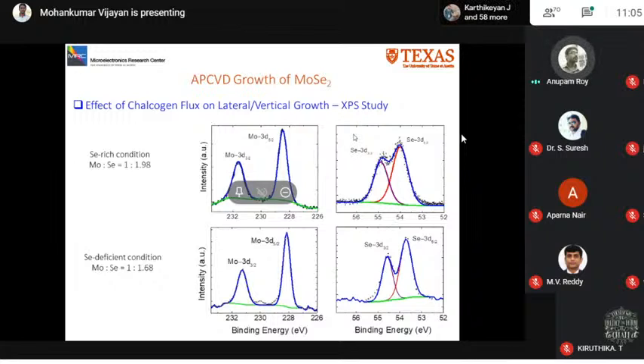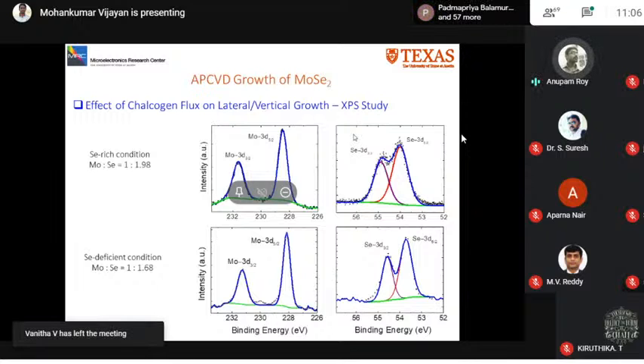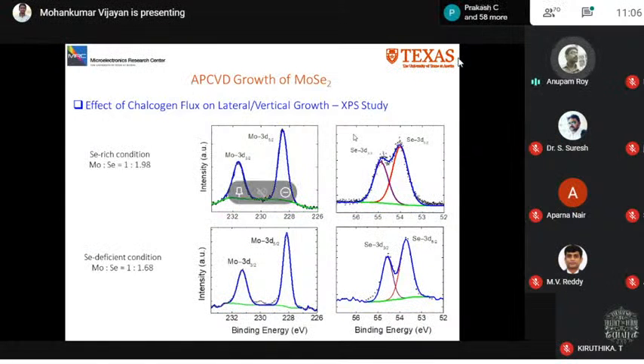For MoSe2 growth under two different environments, selenium-rich and selenium-deficient, we see that when we have a selenium-rich environment, the integrated peak areas of Mo 3d and Se 3d are calculated, and the moly to selenium ratio is about 1:1.98, which suggests that the grown MoSe2 is reasonably stoichiometric. Ideally, it should be 1:2. But for the selenium-deficient condition, it is only about 1:1.68, and so it clearly indicates the abundance of moly-rich nuclei and incomplete selenium passivation.